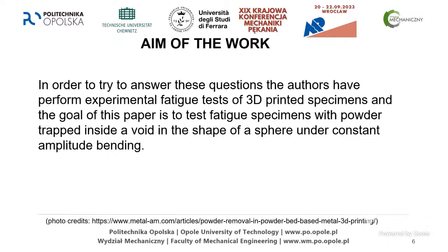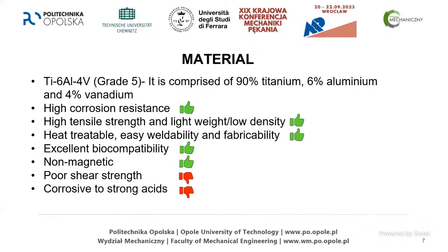So we designed a 3D model, we designed a sphere, but if it's going to be a sphere or not, we will see after the printing process, right? Because the printer also has its capabilities. So the material that we have chosen for this is titanium, right? Aluminium, vanadium, grade 5. It is comprised of 90% titanium, 6% aluminium, and 4% vanadium. The positive aspects of this material are its high corrosion resistance, high tensile strength and light weight, low density, heat treatable, easy weldability and fabricability, excellent biocompatibility. It's non-magnetic. It has some disadvantages as well, such as poor shear strength, and it is corrosive to strong acids.